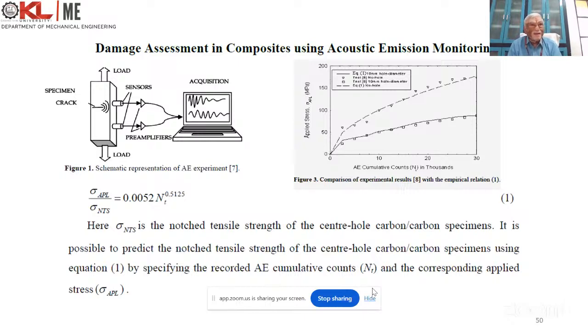Then what happened? As the hole diameter increases, at the time of failure the acoustic emission counts happen to be the same. So near the failure, whether the defect or cutout is there or not, the AE cumulative counts remain constant. That gave the motivation to create the problem. So for different hole specimens, what is the applied stress and what is the strength value related to AE counts?